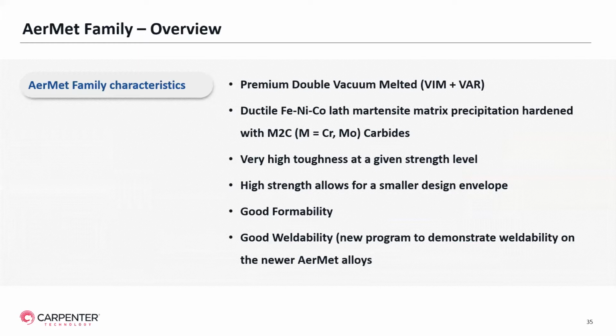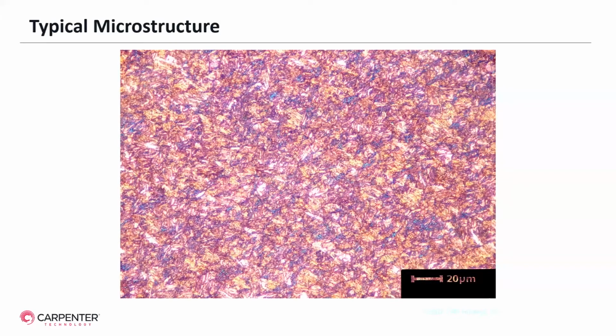As an overview, AerMet is premium double vacuum melted, that's VIM plus VAR. It has the ductile iron nickel cobalt lath martensite that we talked about earlier with the M2C carbides for additional strengthening. It's got very high toughness at each given strength level. The high strength allows for the smaller design. In addition, AerMet provides great formability and good weldability. And right now, we have a new program to demonstrate that in some newer AerMet alloys. The typical microstructure is shown. There's the nickel cobalt lath martensitic structure.